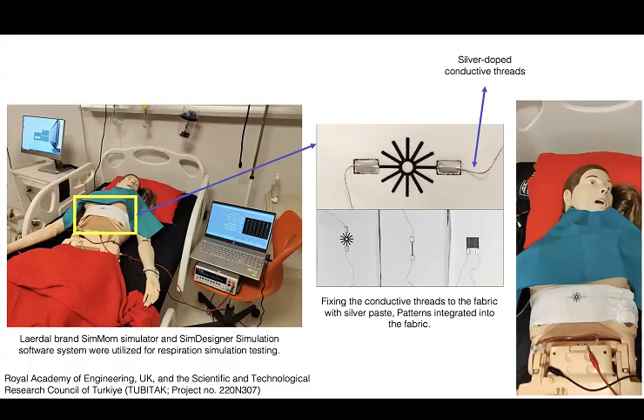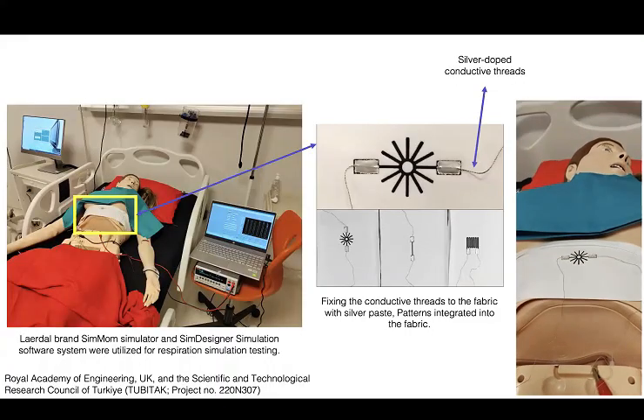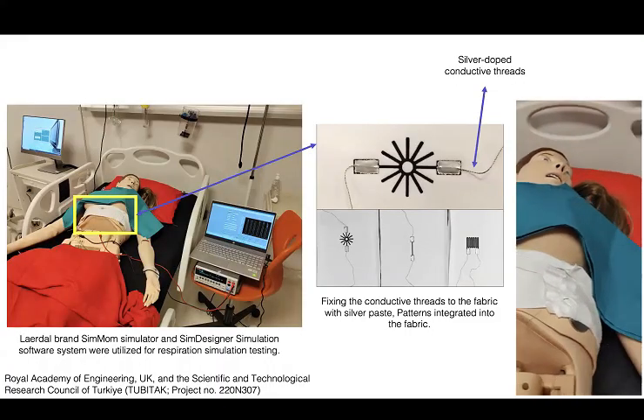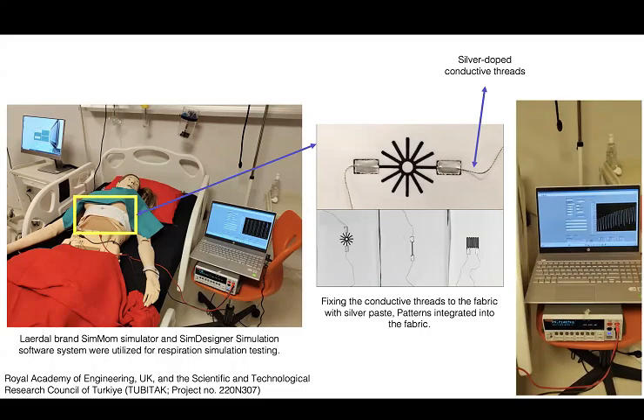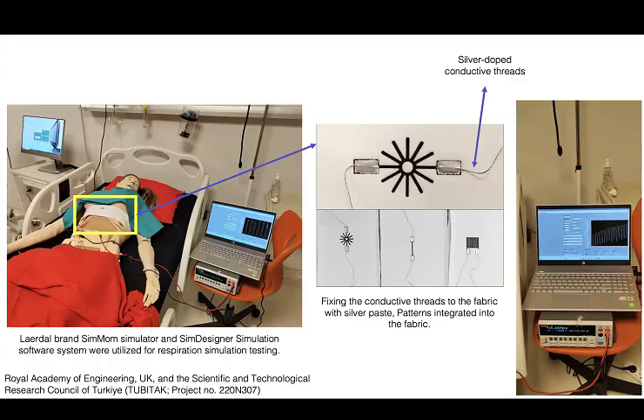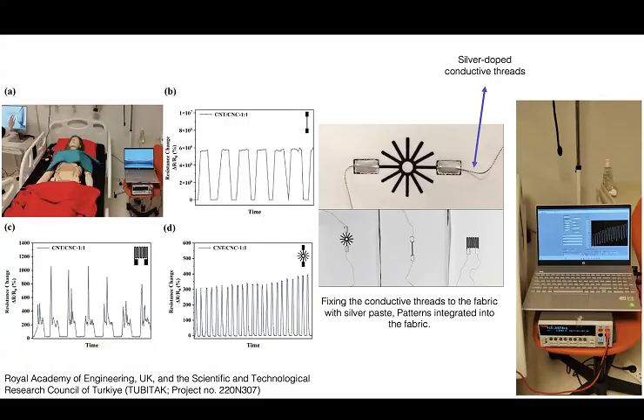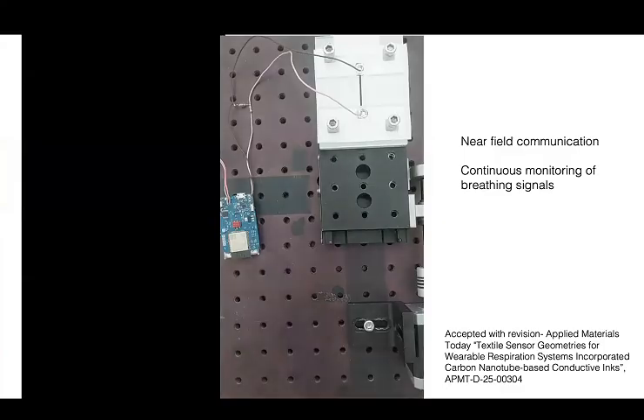So is it this position? It basically simulates the breathing effect and also where you place your sensor. It was a very good exercise for us to understand to what degree we can have quite repeatable results. So you see, we just place the sensors there. Even when we have a response, it needs some kind of data transformation to match the breathing effect, which we can also gather through the simulations on the data interface.